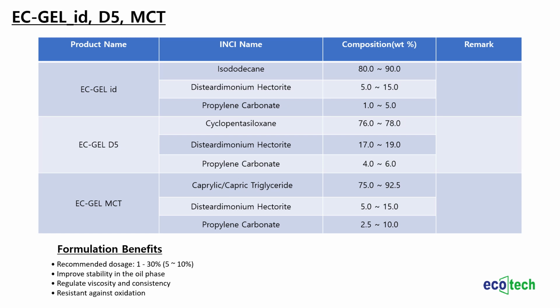Using propylene carbonate as an activator, the layered hectorite swells and exfoliates, allowing the edge-to-face interaction that builds a three-dimensional network. These structures enhance the viscosity and stabilize the oil phase and support the production of elegant and high-performance cosmetic textures, such as balms, sticks, and emulsion-free products.